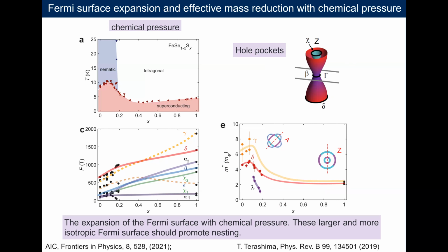Now, this is a summary of all the data on this family of compounds from quantum oscillations. What we have is that Fermi surfaces always expand. So we are going from a strongly correlated system towards a Fermi liquid, and these Fermi surfaces keep getting bigger and bigger. At the same time, the effective masses are decreasing, as we expect as we go towards the sulfur end. But the divergent signatures do not occur at the nematic endpoint. If anything, there seems to be a shift, and the enhancement is inside the nematic phase.